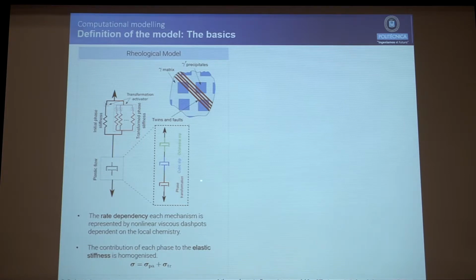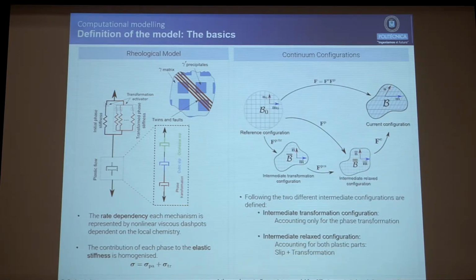And for each of them, especially the phase transformation, this damper, the constant of the damper will depend on the chemistry that is happening locally. So if you are pulling the material really fast, your chemistry is going to be different than if you pull it slower. So we have 4 different configurations: as always, the reference and current configurations, and we have created 2 different intermediate configurations: the intermediate transformation configuration, where we set up our plastic flow rules for the phase transformation, and then a second intermediate relaxed configuration, where we set our power law for cubic slip and octahedral slip.